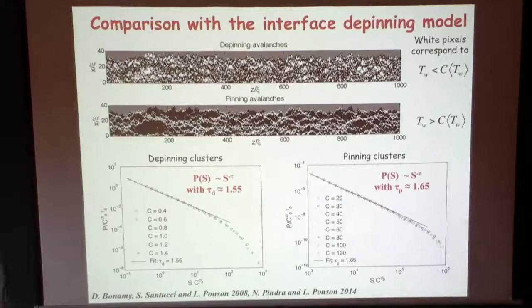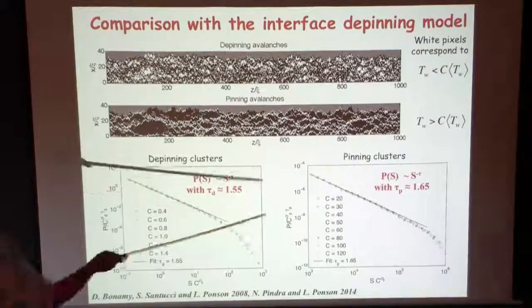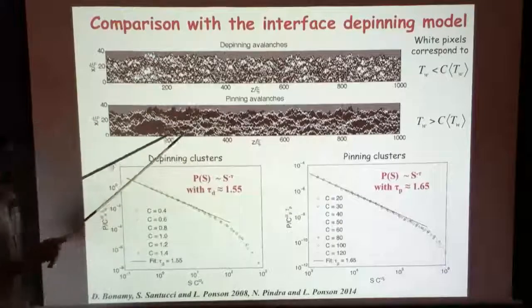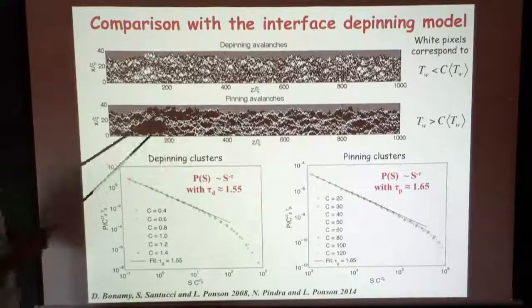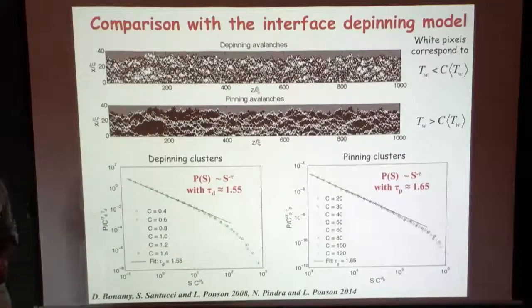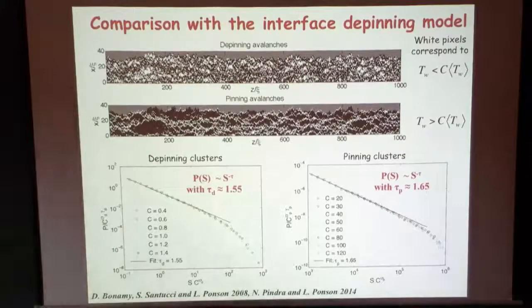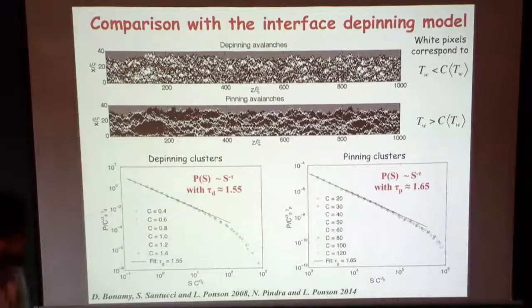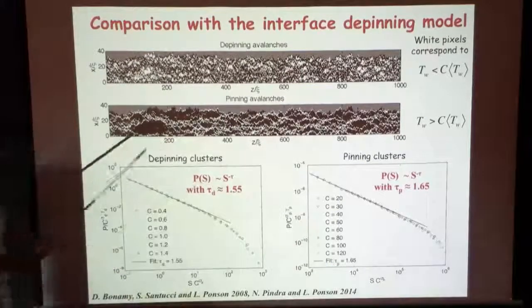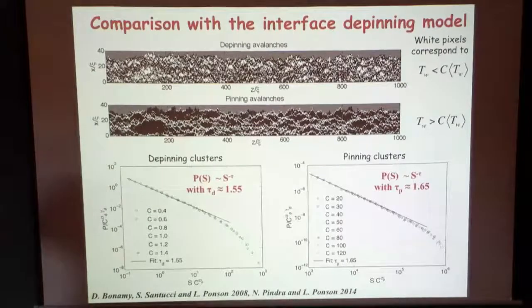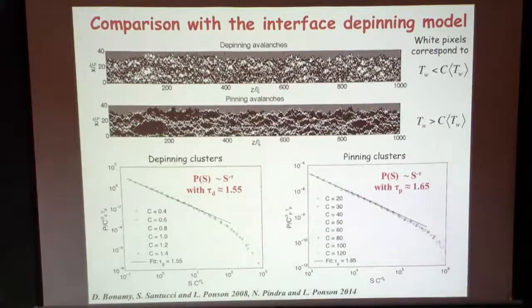On the right would be the black. And from the right, you work on this map. Distribution of the black. No, it's a distribution of the white. Distribution of the white line, or the cluster of white lines. Not a size, it's not an area. It has some very small thickness, but yes, it's more like elongated lines.